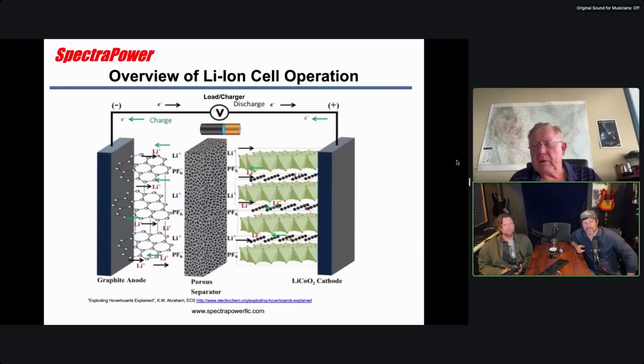It's copper deposited onto graphite? Is that what you're saying? The other way around. The copper foil itself is made through electrodeposition. You mix copper in a solution in a bath, and then you basically submerge a drum in that and charge the drum such that the copper slowly plates onto the drum, and then you peel it off to make this really thin foil. So then you encase that foil in the graphite.